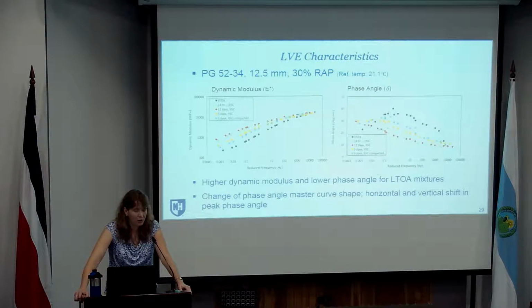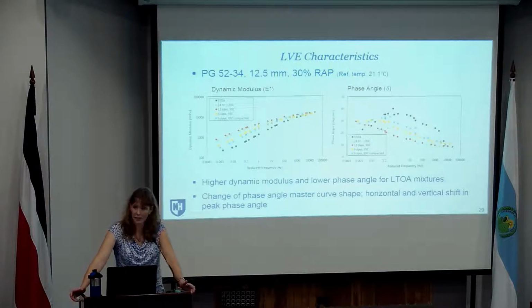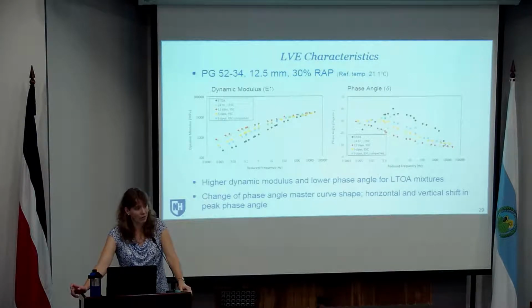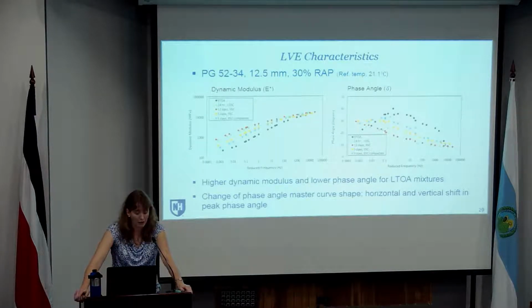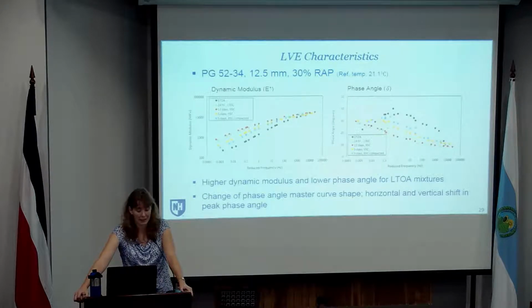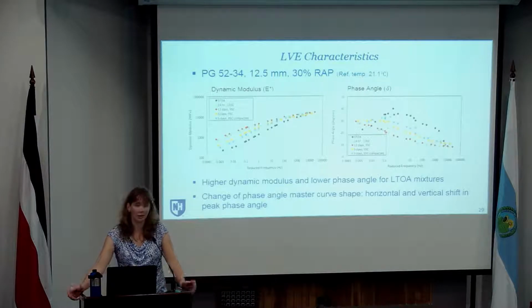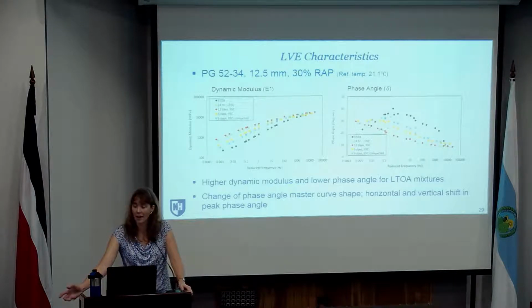So for the dynamic modulus curves, you can see, not unexpectedly, as you increase the aging level or increase the amount of laboratory conditioning that's done, you've got an increase in stiffness. And we did see that the 5 days aging compacted and the 5 days loose had very similar results in terms of the stiffness. Statistically speaking, we couldn't say that there was a difference between those two. Also interesting that the 12 days at 95 degrees C were statistically similar to the 24 hours at 135. And again, this was for that whole range of mixtures that we tested. So we're pretty confident in those two aging protocols, just for whatever reason, they happen to basically produce the same level of change in the mixtures with respect to our dynamic modulus and our phase angle.